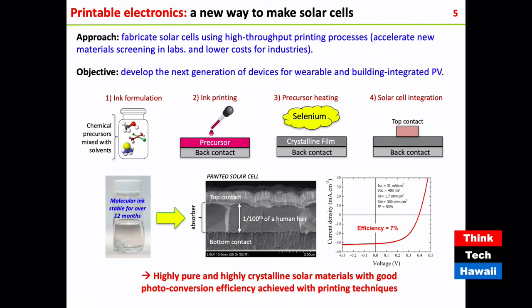So you start with an ink that contains a solvent and the raw elements, the chemicals. We essentially spin coat or print this onto a substrate to build up a layer, and then do a very quick, about 15-minute annealing in a specific atmosphere. Annealing is like putting it in a heat chamber, fixing it, drying it out. That way we form a crystal which, in some cases, is as good, even sometimes better in terms of crystal size than the material we would get in a vacuum chamber. So we're getting very close to the quality of film that you would get in a vacuum chamber.